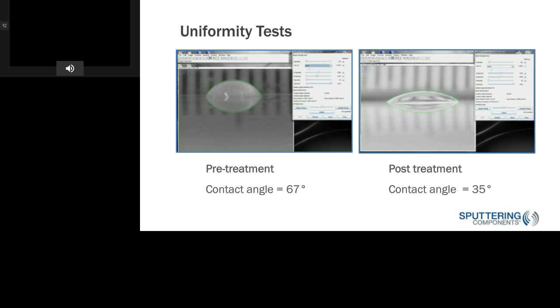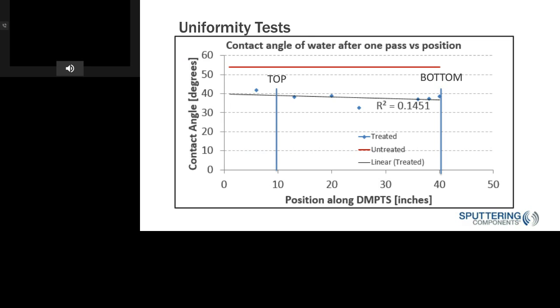Next slide. And here's a graph just to show that. So you can see along the x-axis, the position along the DMPTS, which is equivalent to the position along the substrate, and then the contact angle on the left. So this is just after one pass, and you can see the red line is the untreated substrate, and then the measurements that we took on the treated substrate. You've got the top of the substrate on the left and the bottom of the substrate on the right, so you can see that the contact angle decreased all along pretty uniformly.